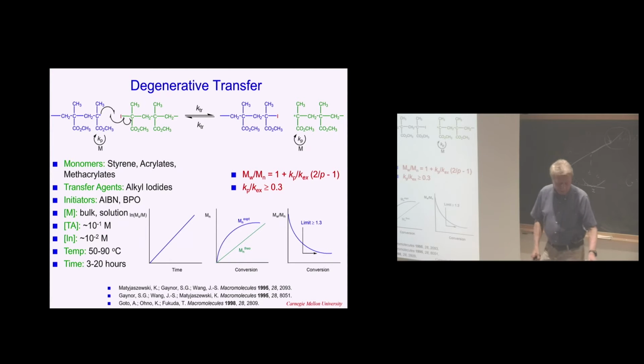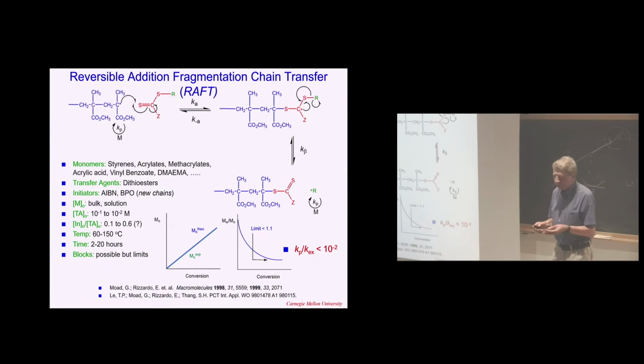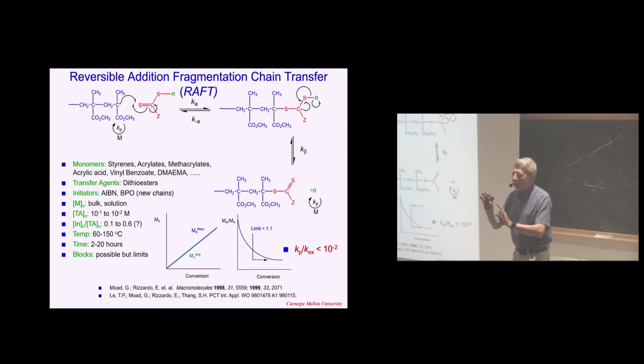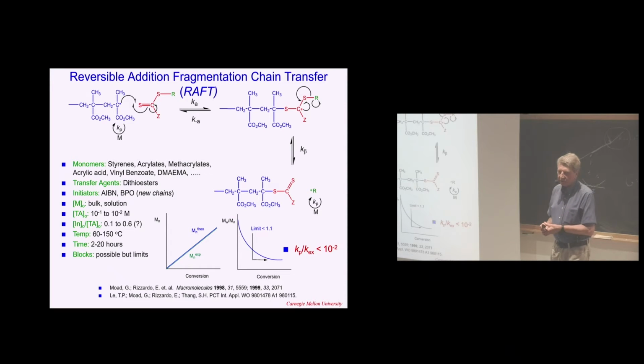So in 1998, in Australia, they developed a process which is called RAFT, or Reversible Addition Fragmentation Chain Transfer process. And now this species, which contains this double bond, this sulfur-carbon bond, is much more reactive towards radical. So you could see here that now this exchange reaction is 100 times faster than propagation. So if I keep the concentration of monomer to chain transfer agent 100 to 1, I would add 1, 2, 3, 4, 5, and all chains would grow perfectly with conversion, and dispersities can be 1.1 or sometimes even less.